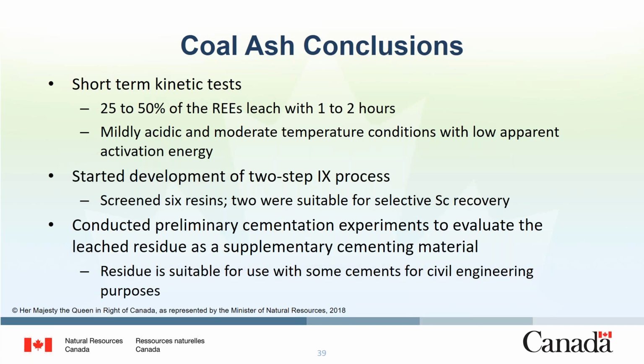In terms of conclusions from our fly ash study, from the short-term kinetic experiments, we leached 25 to 50% of the REEs within the first hour or two, with mildly acidic and moderate temperatures, with low apparent activation energy. So it really suggests a low energy process is suitable for processing this material.